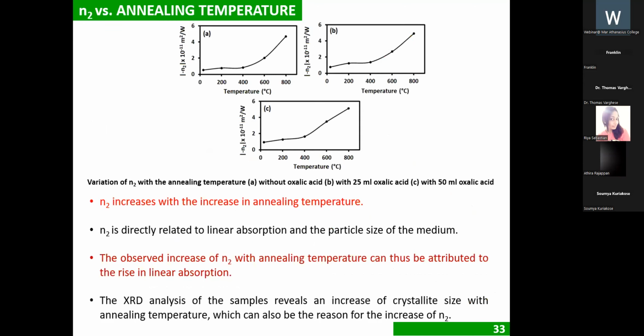Then the variation of N2 with the annealing temperatures is here. In all the samples with a different amount of oxalic acid, N2 enhancement can be observed with the temperature. It's mainly because of an enhancement in alpha. Alpha has a direct effect on N2 in the case of thermal nonlinearity.